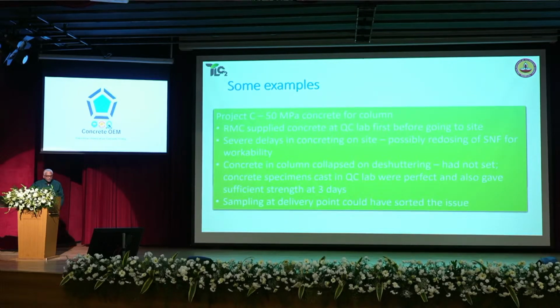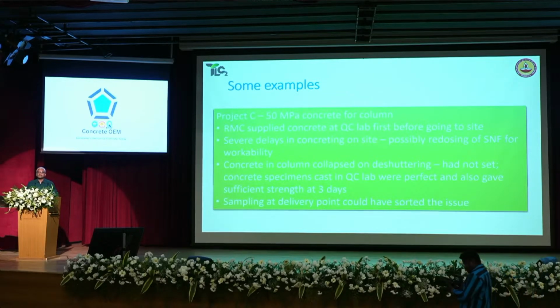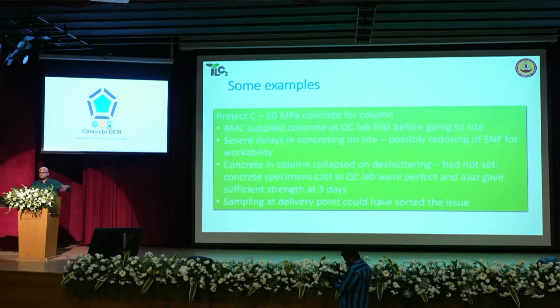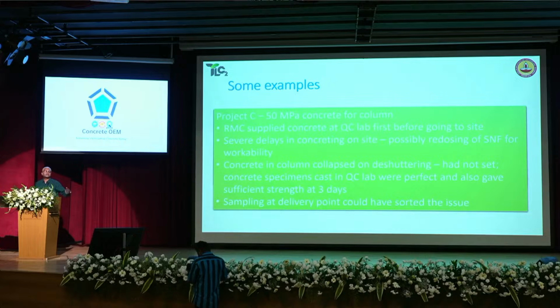In this third project, 50 MPa concrete was supplied for a column. So as is usually the case, the truck arrives on site. First it goes to a QC lab, dumps the concrete required for preparing your cubes and cylinders and the other quality assessment in terms of workability, then it goes to the site and delivers the concrete. In this case, as it turned out, when it went to the site was not prepared. The reinforcement was not ready, formwork was not properly ready, and so on. It took some time for the concrete to be actually put in the structure.